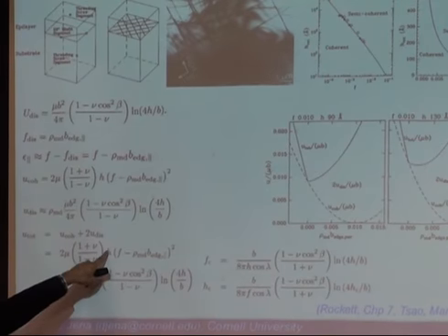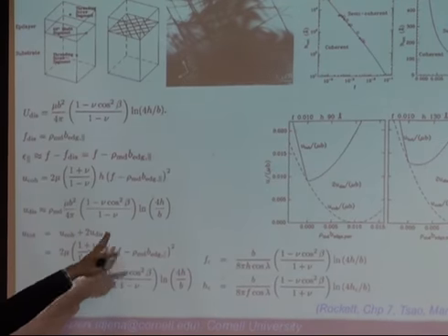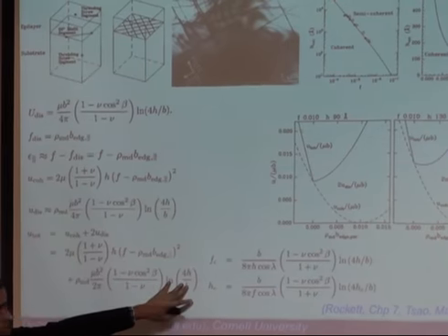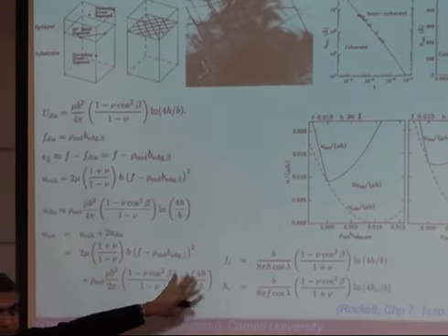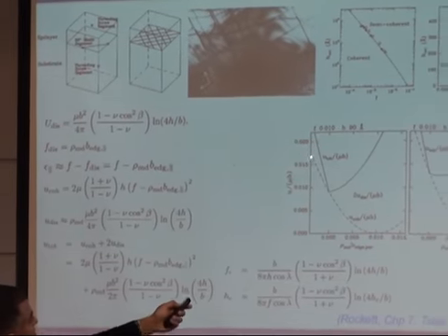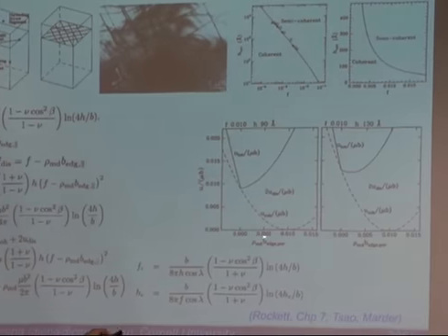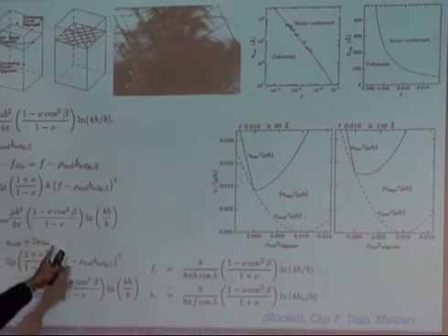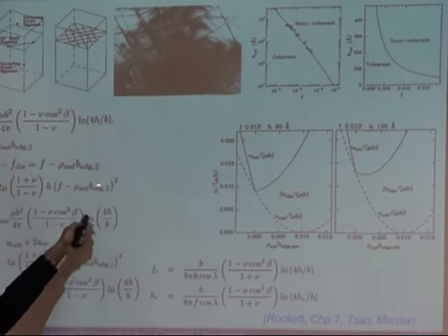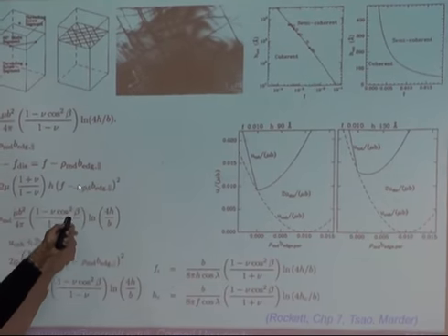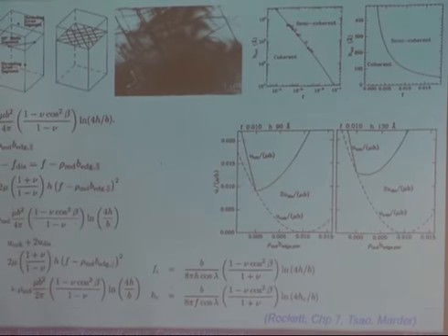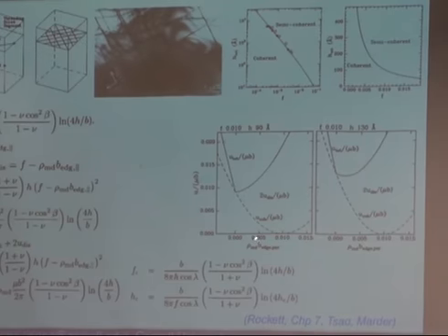Right? So the height term here is increasing linearly. Here it's increasing logarithmically, right? And you make a plot of this. Here's the plot. This thing is because of coherence. It goes as a parabola with the number of dislocations, or the density of dislocations. It's pretty clear. It's just a square of that. Its minima is not at 0. It's a shifted parabola. It's somewhere there, right?